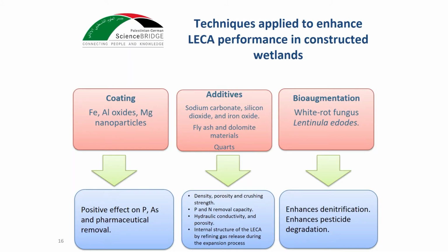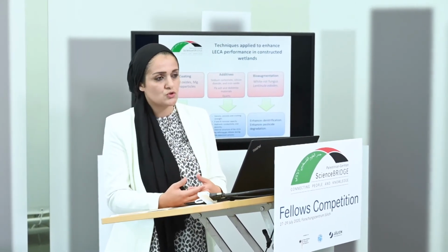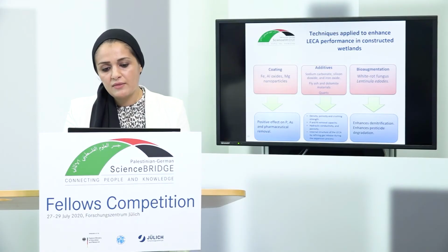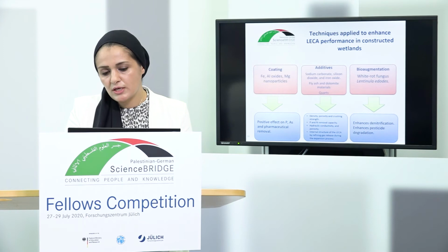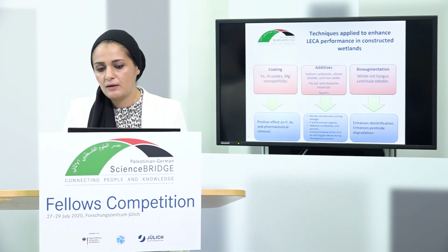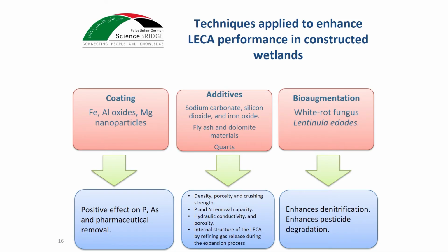They also use additives, adding materials like carbonate, iron oxide, fly ash, and quartz in the production phase to enhance the physical characteristics of LECA. The latest is bioaugmentation, where they inoculate this material with a fungus, which was found to enhance denitrification and pesticide degradation.